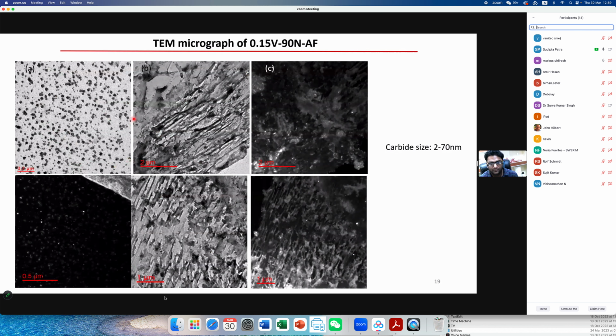Now, the TEM micrograph from 90 nitrogen, we have observed from the extraction replica technique we are using here, and we have observed some cuboidal and irregular shaped precipitates. Sometimes it is very high in concentration in a few places. In the pearlite region also we have observed some precipitation. The size range is 2 to 70 nanometer. In the dark field images also we can observe that some precipitates are coarser and some are very fine.